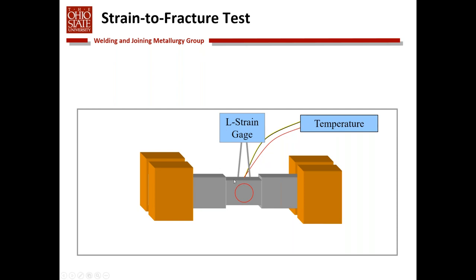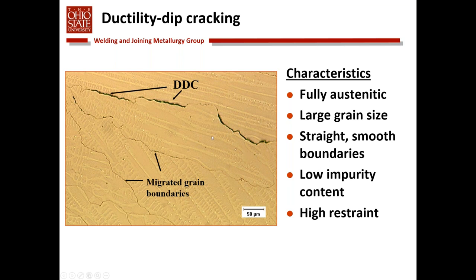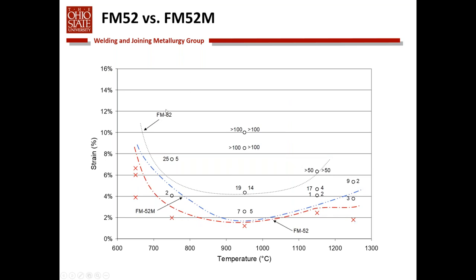You can use an L-strain gauge. We also put die marks on the gauge section itself so that we can do a physical measurement. We heat that sample up, we pull it, not to failure, but we strain it to a certain degree, and then we examine the sample to see if cracking has occurred. These are the types of cracks that we can develop in the strain to fracture test. This is for evaluating weld metal ductility dip cracking, and you see the cracking occurs along these migrated crystallographic grain boundaries in the weld metal. And this is the type of data you can generate.